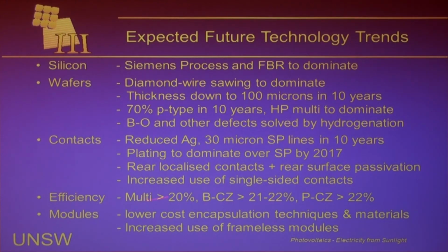And so these are the types of predictions now. Here's the P-type that's boron doped. They're the P-type Czochralski wafers, 21 to 22. The phosphorus doped, which are the N-type, still above 22 is what's predicted. Multi, which are a lower cost wafer, they're no longer a single crystal. They're the high performance multi that I was talking about. It's a lower cost but still quite good quality wafer, is expected now to get over 20% efficiency.